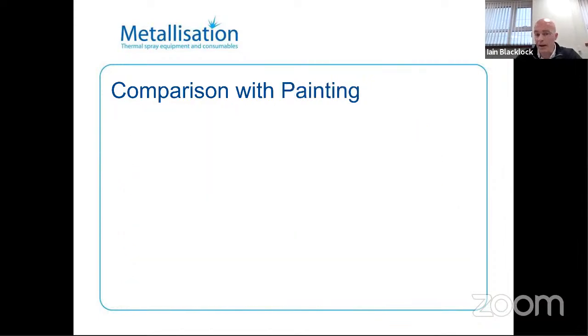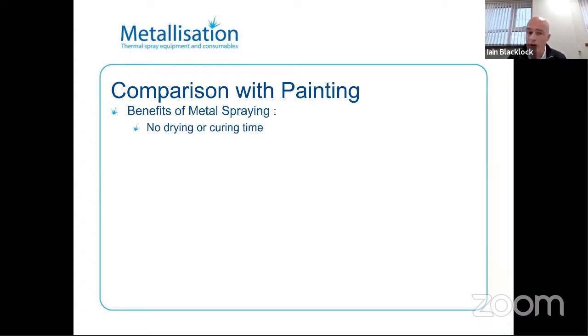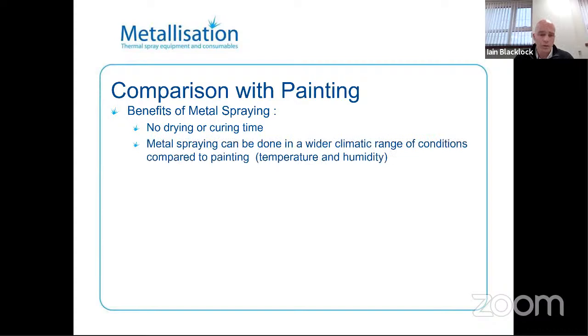Now onto the comparison with painting. So the benefits of metal spray. We've got no drying time, we've got no curing time. You grit blast, you metal spray, you spray the zinc, and instantly you have a coating, which you can measure, and you can then move to the next stage of the process. There's no dwell time, you don't need to leave it standing round. It's as instantaneous as that. It can be applied in a wider climatic range of conditions compared to painting as well, as far as temperature and humidity.